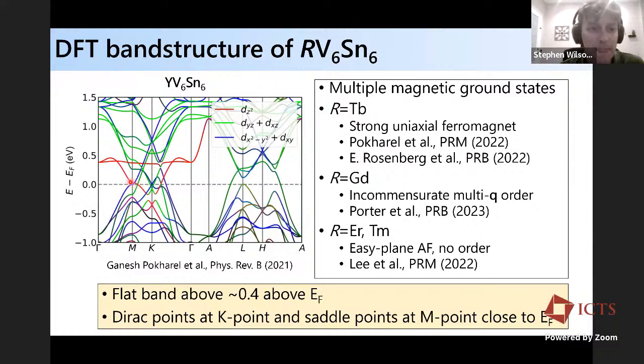And again, you have these Van Hove points, which are close to the Fermi level. And you also have more of a flat band feature, which is further away. And you can see, again, the Dirac points here at the K points. By changing the rare earth, for instance, you can put terbium or gadolinium or erbium, and you can get a lot of different magnetic behaviors in the system. But in the case of the yttrium compound, basically nothing happens. There are no phase transitions that have been identified in that system, okay?